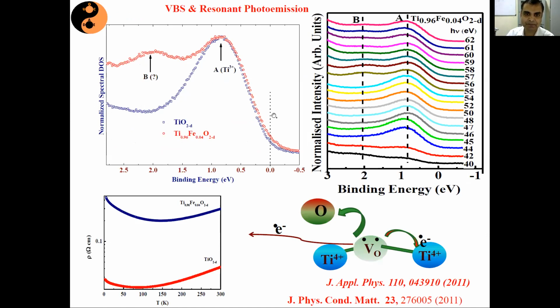at room temperature. Now, this is very intriguing because we know that TiO2 has a wide band gap of 3.4 electron volt. But as I discussed yesterday also, if in my system we have sufficient oxygen vacancy densities, then those oxygen vacancies form a shallow donor level just below the conduction band, and they can give rise to sufficient free electrons. And if the density of such oxygen vacancies is very high, then they can just merge or coincide with your Fermi level.